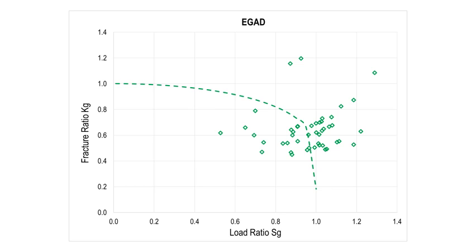Now, the benefit of having an assessment diagram for your pipeline integrity work is that you can do predictions. So what I did is for each one of my 48 data sets, I actually used the goal seek within the Excel spreadsheet to figure out for each one of these data sets what combination of parameters would put me exactly on that critical EGAD K-limit. And if I do that, then I essentially come up with a predicted failure strength. If I then take the EGAD predicted failure strength and I map it against the true measured failure strength, I can get a sense of how well the model is validating. So I'm going to do that next.